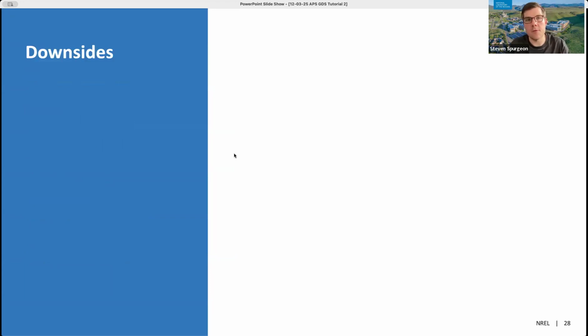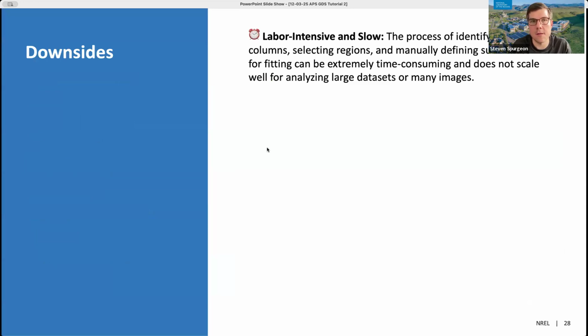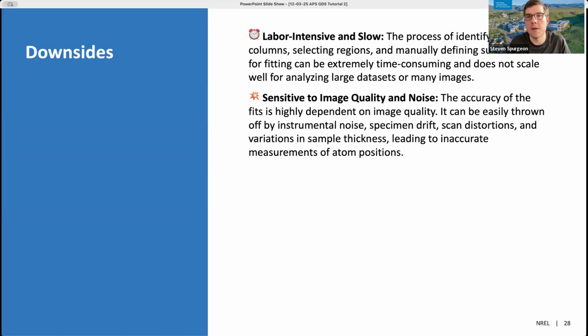So the important point of why I show this is that this is kind of the first starting point for many microscopists who start to employ statistical methods. And there's some downside to this process that we very quickly learn. First thing is that this process of regression is very labor intensive and slow. And so identifying columns, defining sublattices, doing the fitting can be very time consuming, and it doesn't really scale easily without fine tuning to many other types of images or even images of the same material. It's highly sensitive to image quality and noise.